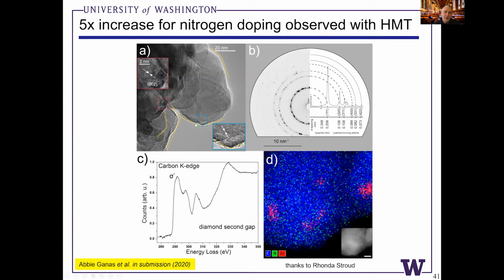And one thing I wanted to share today is this really beautiful TEM image that our collaborator Rhonda Stroud took at the Naval Research Lab. You can see these very sharp facets at the surface of the diamond that we make. If you zoom in and look at the high-res spectrum, these are 111 planes. We think this is most likely a 111 facet of the diamond, which is consistent with what you see in a detonation material or a milled sample.